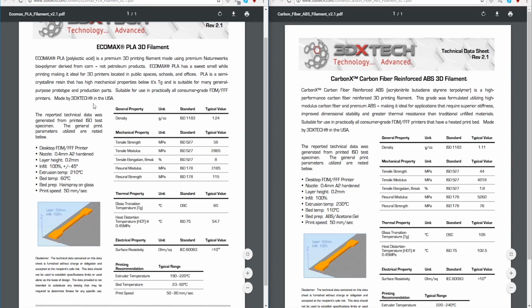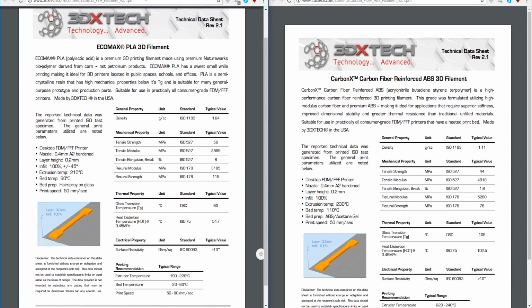It's about the same as ABS, which we saw PLA versus the carbon fiber PLA. Because the matrix is the part that fails, so when you have a reinforced material, you have the matrix and then you have the reinforcement. The matrix is basically the resin, and the reinforcement is the carbon fiber. So your ultimate stress has to do with your matrix. So your ultimate stress doesn't really increase from reinforcing. What does increase is the stiffness of that material. So you want that material to be very flexible and the material put inside to be very stiff.